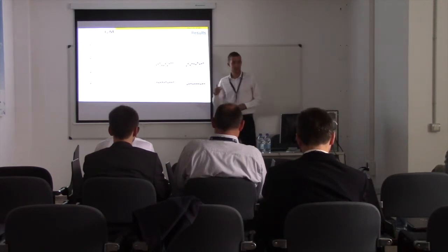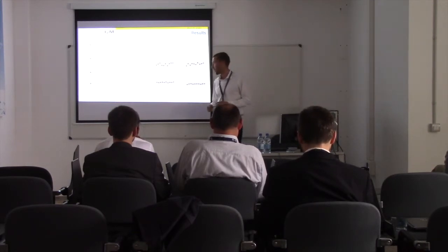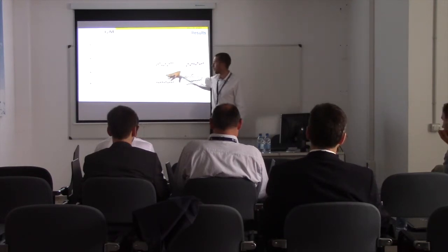Also, for these different systems, you can see that we had a larger packing density for low velocity displacement, which is associated to arrangement mechanisms between the particles. Roller can compact this powder bed layer more efficiently, and also we can increase the powder bed layer during the process. As you can see, we always have a similar shape for the different systems and for the different speeds.